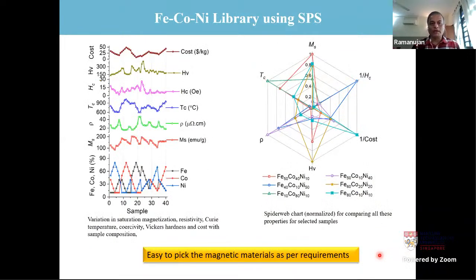So using this, we can again have this radar plot and identify compositions which have single good properties, right? So you can identify from this method in this ternary space. And it's not only ternary, you can go to quaternary, you can add boron, you can do other stuff. So this methodology is quite general and not only applicable to iron, cobalt, nickel, we are also applying it to the iron, silicon, aluminum, which is our classic transformer steel, and trying to find out new compositions which can have excellent combinations for the iron, silicon, aluminum case as well. So this is a broad methodology which can be applied to other material systems.